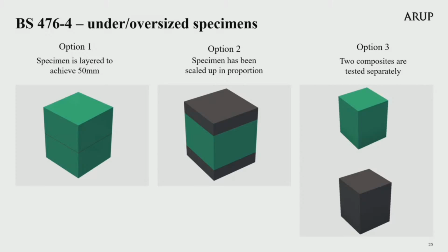For composite materials of a thickness such that an integral number of layers cannot be put together to give the specific size, the thickness of the different components should be adjusted so their proportions remain the same as the original specimen. If either of these options cannot be followed, the test must be performed on the individual component layers of the material and reported accordingly.